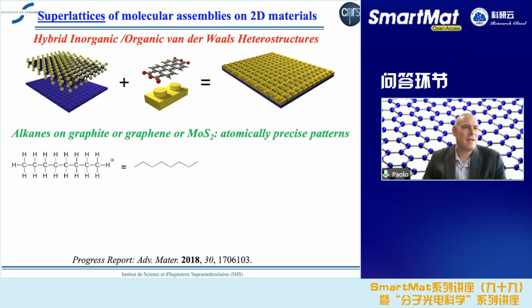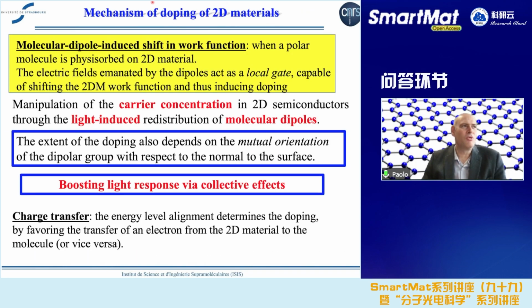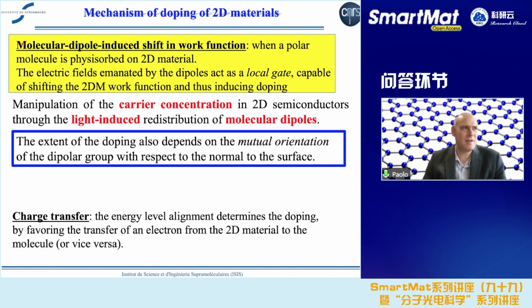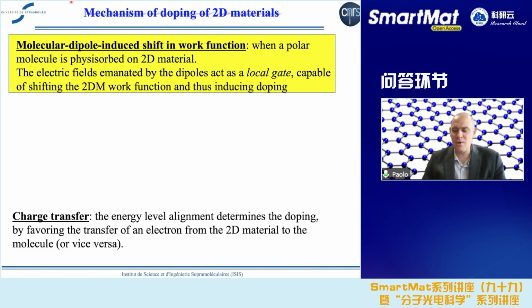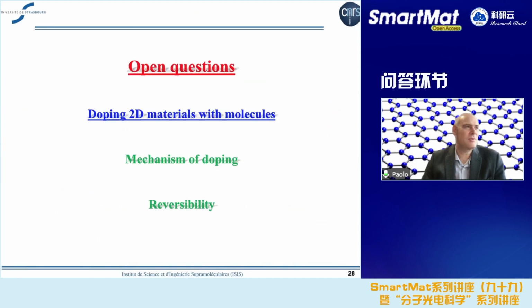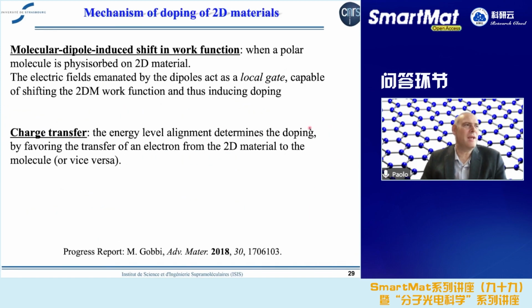So actually, I think if you want to dope the material, let me go to this slide. You can use, let's say, dipoles, or you can use charge transfer phenomena. If you use dipoles, the effect is collective. And so if you are looking for a collective effect, you need to have ordered films. If you use charge transfer processes, here you don't need ordered films.